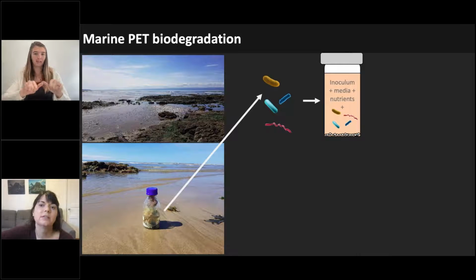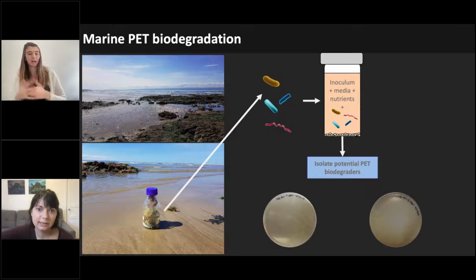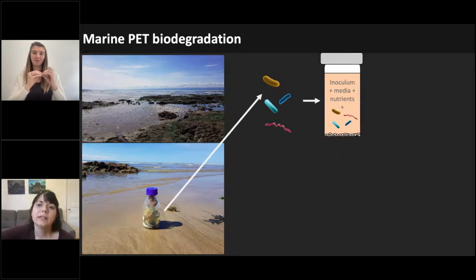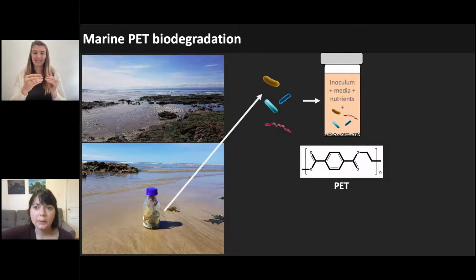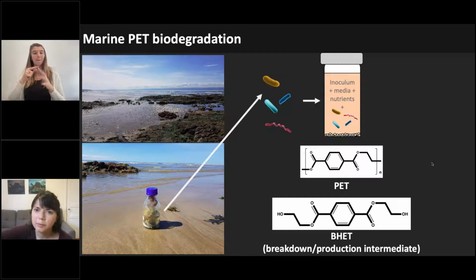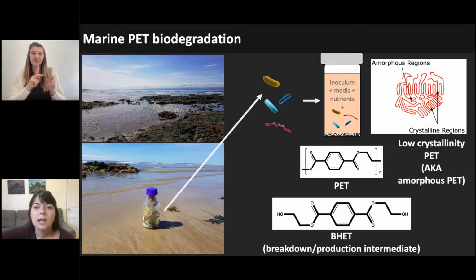And then as a second objective, I used the same setup to try to isolate some bacteria that might be able to degrade PET. And in both parts of this, I used both PET and also BHET, which can be both a breakdown product and a production intermediate of PET. And while I did use a few different types of PET, what I'll be focusing on today is low crystallinity PET. And so the crystallinity just refers to how tightly packed the chains of the PET are. So in the case of the low crystallinity PET, more of the chains are quite loosely packed, which just makes them a bit more accessible for microbial attack.